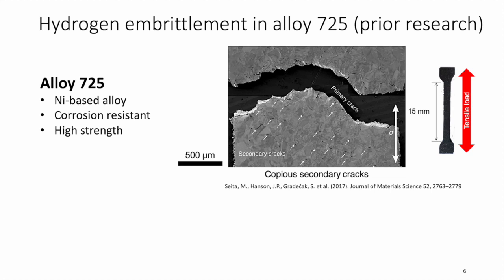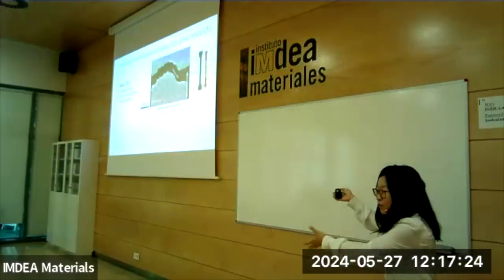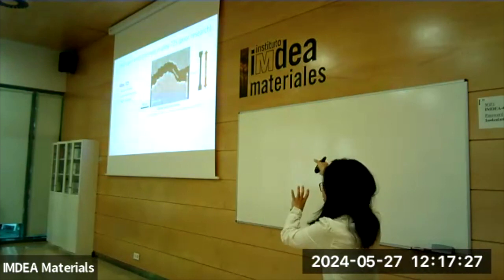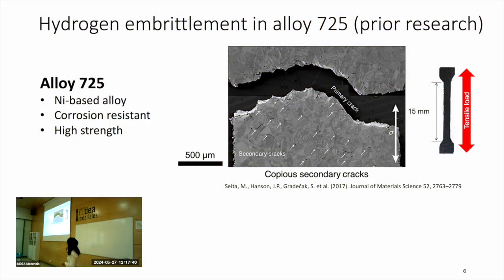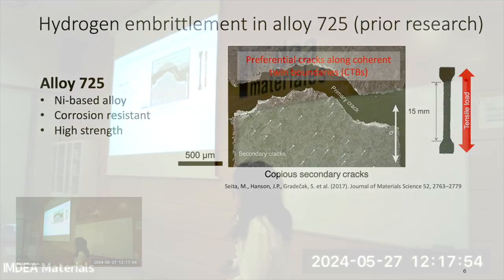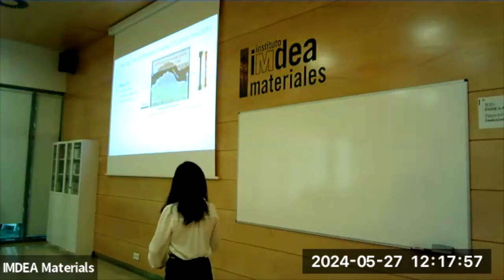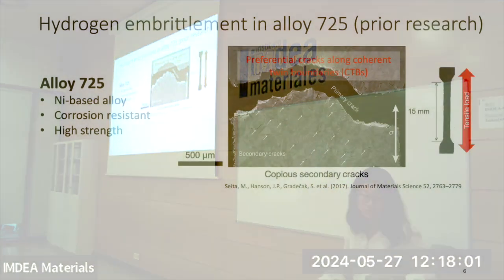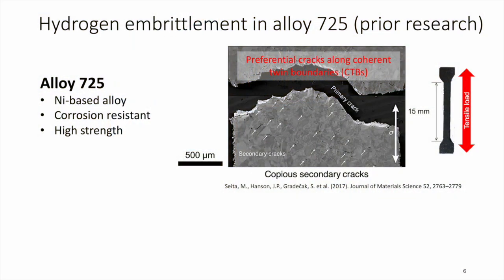Regarding the material of our interest, alloy 725, this is a nickel-based alloy with good corrosion resistance and high strength. And in industry, people use it as a structural material. So you definitely don't want the sudden failure in the picture we showed before to happen to this material. In the prior research, people charged it with hydrogen and then did a tensile test, and saw copious secondary cracks on the surface with a primary crack in the middle. They did some post-tensile test analysis and found preferential cracks along the coherent twin boundaries, which we call CTB. CTBs are the ones with the lowest energy, which means they should be more resistant to hydrogen embrittlement.